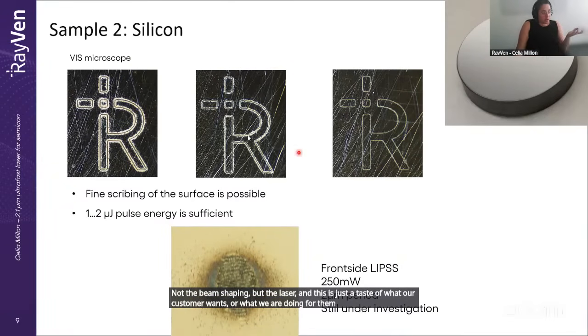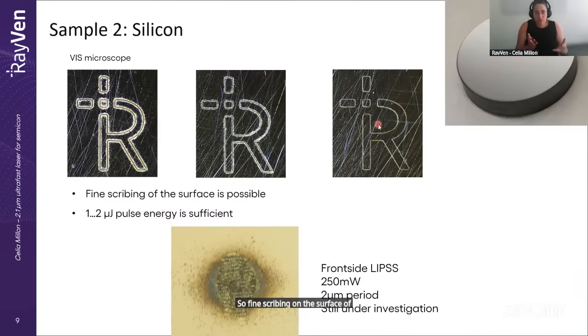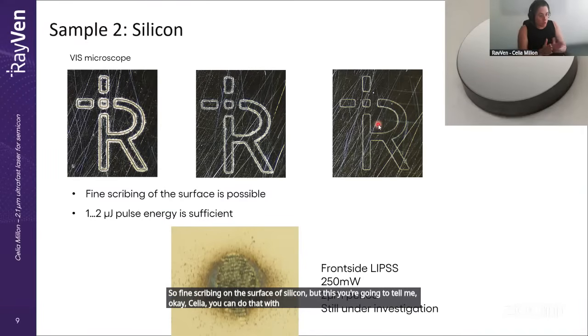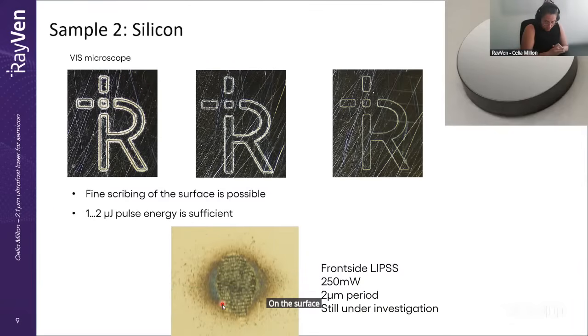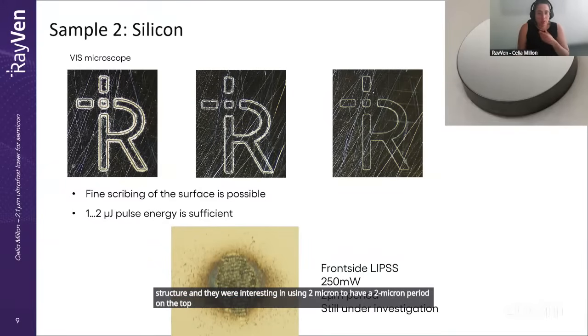So fine scribing on the surface of silicon, but you're going to tell me, okay, Celia, you can do that with a 1 micron system, sure. But where they were mostly interested is to do some LIPSS on the surface, mostly for having anti-reflecting structure. And they were interested in using 2 micron to have a 2 micron period on the top of the samples.